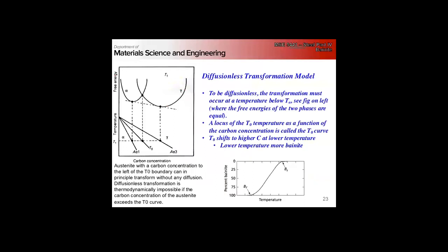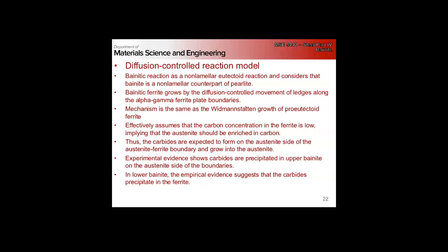Okay. Yeah, austenite. Yeah, so if you're partitioning carbon out of the ferrite, you're going to have an elevated carbon content just on the austenite side of the interface relative to the bulk carbon content, because you're partitioning out, but it hasn't diffused away yet.